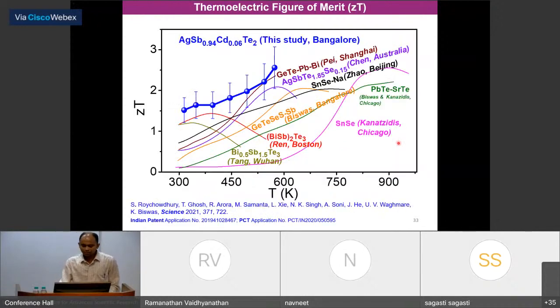So let's compare with all the state of the art. So this is all the state of the art data to this date. So basically, this is our data. In the mid temperature range, our data actually outperforms all the materials. But we have important data from Kanatzidis group from Chicago, lead telluride based material, SnSe from Beijing group, and also bismuth antimony telluride from Wuhan, and bismuth antimony telluride from Boston. And we have other data in germanium telluride from Bangalore, as well as Pei group in Shanghai published data on germanium telluride, which has a similar ZT. But our average ZT is very high compared to them, because from low temperature to high temperature it shows a flat kind of ZT, which is actually important for application.